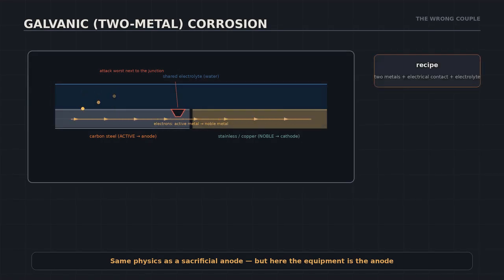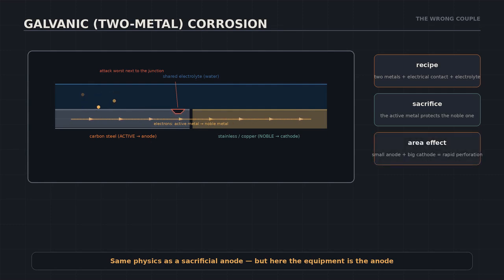Galvanic corrosion needs 3 ingredients: 2 different metals, electrical contact between them, and a shared electrolyte. The less noble metal becomes the anode, and sacrifices itself to protect the nobler one. The worst-case geometry: a small active area coupled to a large noble one, like a few steel bolts in a stainless assembly, the bolts perforate fast. The fixes are elegant: electrically insulate the joint, or choose metals close together in the galvanic series. Same physics as a sacrificial anode, except here, your equipment is the anode.